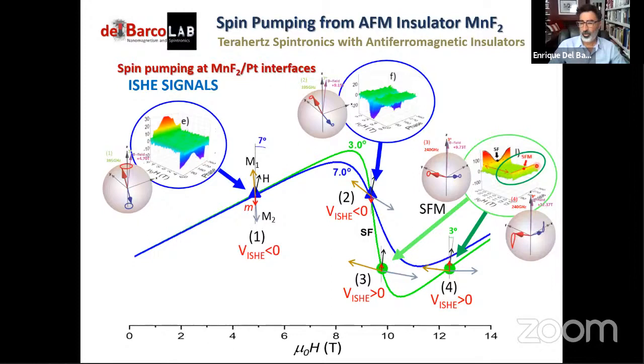And what it makes us to believe that the reversal of the sign of the inverse spin Hall effect voltage and this positive voltage that we obtain in the quasi-ferromagnetic mode are most likely coming from the spin Seebeck effect. So the spin Seebeck effect is going to be stronger when we have a system developing an equilibrium magnetization. Remember now the magnetizations are canted slightly towards the magnetic field. That equilibrium magnetization can give rise to a much stronger spin Seebeck effect in the material.